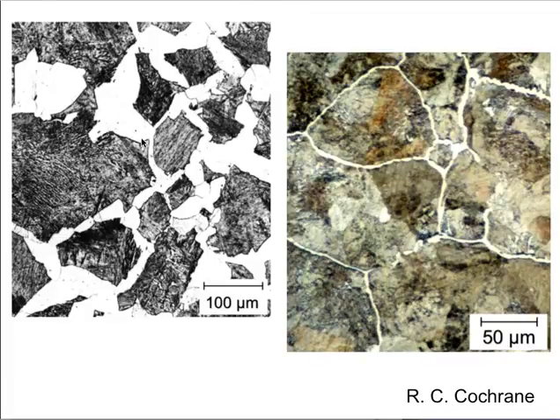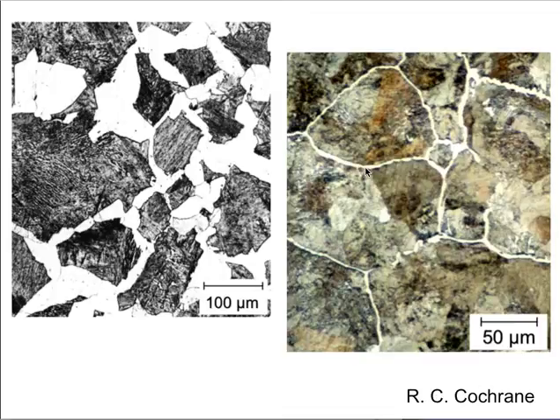This is a steel with a low carbon concentration; this is a steel with a high carbon concentration where the growth rate is slower. Therefore you get thin layers of ferrite at the austenite grain surfaces. The rest of it is pearlite.